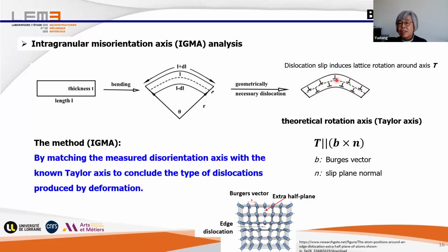In fact, you see the rotation axis is parallel to the dislocation line. People call this the Taylor axis. This Taylor axis can be calculated using the Burgers vector b and the slip plane normal n here. The method works like this: we measure the orientation of different parts, and we analyze with the software to get the disorientation angle and axis. Then we match the calculated angle with the type of dislocation lines produced by deformation, and then we can resolve which kind of slip was activated.